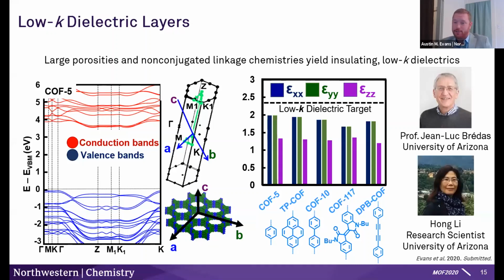But actually, they still have interesting electronic properties, even in the absence of being conductive. As a function of their high porosities and the fact that they don't include any polarizable bonds, I mean, metal coordination bonds are a bit more susceptible to that side of things. But when you have a fully organic network with a high level of porosity, the dielectric constants are quite low. So I've included some calculations from our colleagues in the Breda group where they've essentially found that all of these COFs, it's a variety of COF structures, are well below the low K dielectric target in all of their crystallographic vectors.